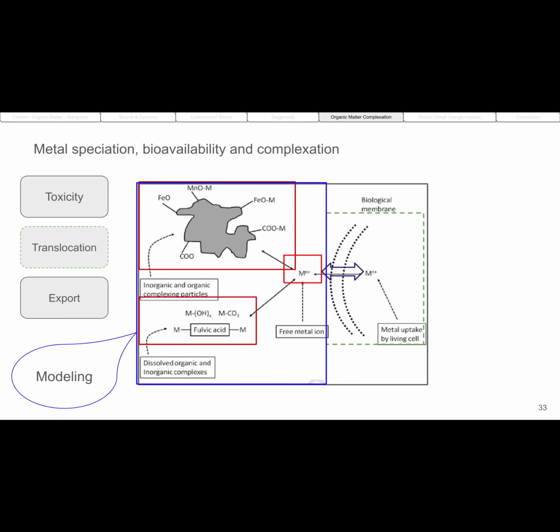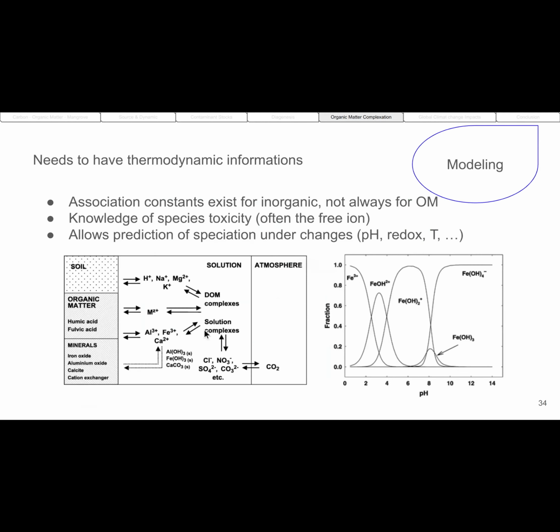The last way to get the speciation between organic matter and metals is the model, in fact, modeling the system. You need to have a lot of information. It's very hard work to get. But in fact, if you have all the association constants and the concentrations, you can predict, as on the right graph, the speciation of your metal, and you can also predict this speciation under changes in temperature, pH, or redox. The only problem is that all the inorganic ligands are generally well known, even the adsorption on solids, etc., but the least known parameter in this system is the interaction with organic matter.